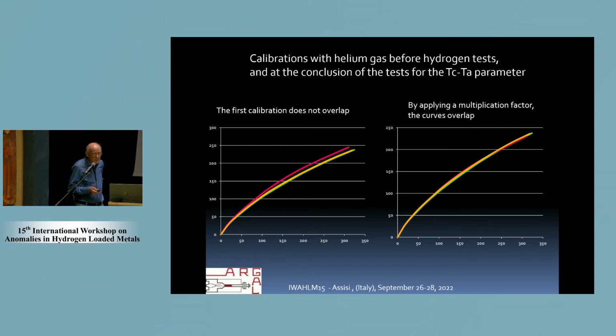The same is not true for the external temperature of the reactor, because there is a small shift between the first calibration and the final calibration in helium, due to a small change in the color of the external surface of the reactor. To have a reference for the results in the experiments, we can overlap also the three calibrations using exactly the same approach of a multiplicative factor, a very simple mathematical operation.